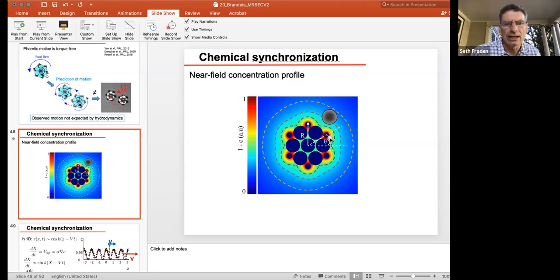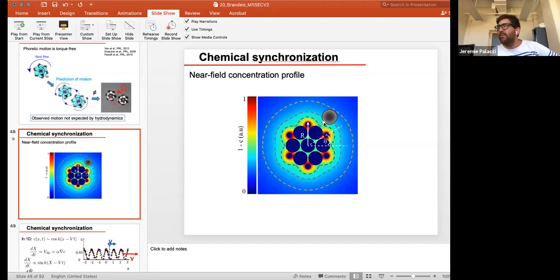Yeah. So here, what about the rotation rate? What rotation rate did these objects have? So the rotation rate, that's a good point. You will see in the paper, we dismissively discuss that we are not quite there. We capture the synchronization very well. The rotation rate we observe is not quite the one we would predict from that picture by a factor of 10. We are 1 order of magnitude off, and we suspect it's hydrodynamics.